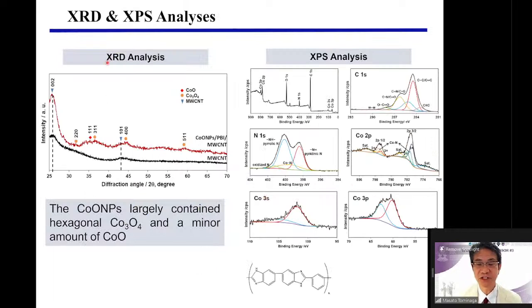This is a result of XRD and XPS. From the XRD result, I can say that these cobalt oxide nanoparticles are mainly Co3O4 and a minor amount of CoO. Mainly Co3O4. And from the XPS result, I can say the cobalt oxide nanoparticle is fixed to this polymer, because I can see a Co-N bond here in the N1s peak. Also, in the Co 2p peak, we can observe a Co-N binding peak here.